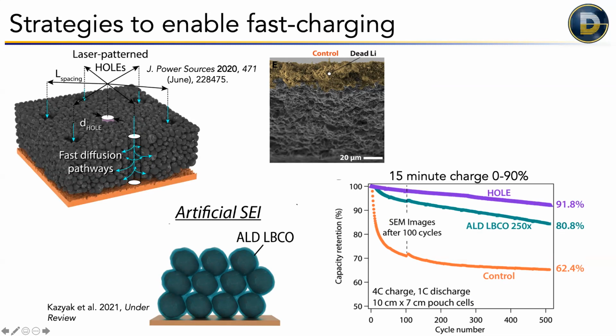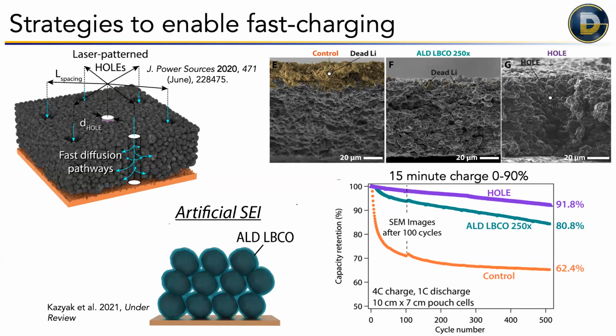And then another approach here that we developed last year is basically using a laser to cut holes to allow the lithium ions to get deeper into the electrode. And that works even better. We can even go to 15-minute charge and still have 90% capacity after 500 cycles. And this is really a game changer for electric vehicles because of the fact that it alleviates range anxiety. And just kind of showing you here, rather than this thick layer of dead lithium, there's just a little bit sprinkled here and almost nothing on what we call this highly ordered laser patterned electrode or hole electrode.